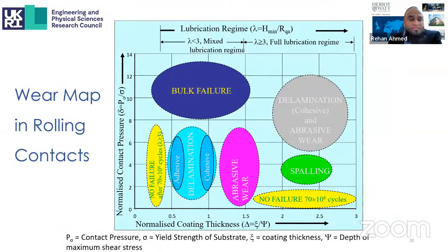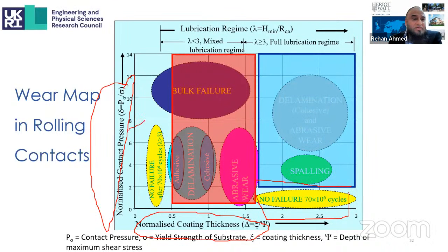So in order to map the failure of these coatings, we have to use non-dimensionalized maps, and I have normalized the contact pressure here with the yield strength of the substrate on the y-axis, and then I've normalized the coating thickness with the depth of the maximum shear stress. Once we do that, we can map out the different types of failures, and we can then try and design coatings where it is very likely that we are not going to have any failure, for example, as shown by these yellow areas. And then the blue and the red areas are the areas which really need to be avoided in the design process. The lubrication regime is shown as the secondary axis in this particular slide, where the full lubrication regime indicates that there is no asperity contact between the ball and the coating surface.